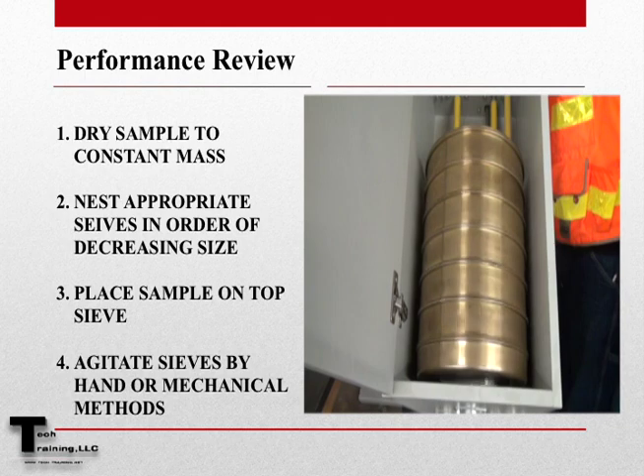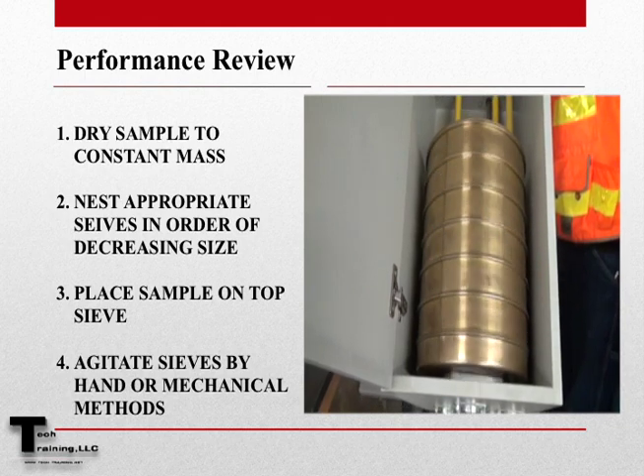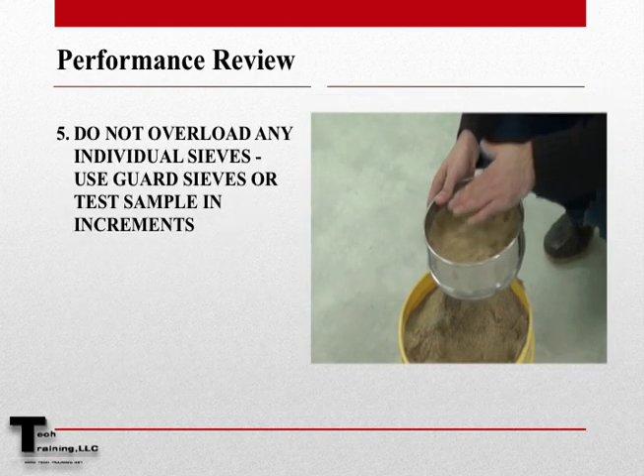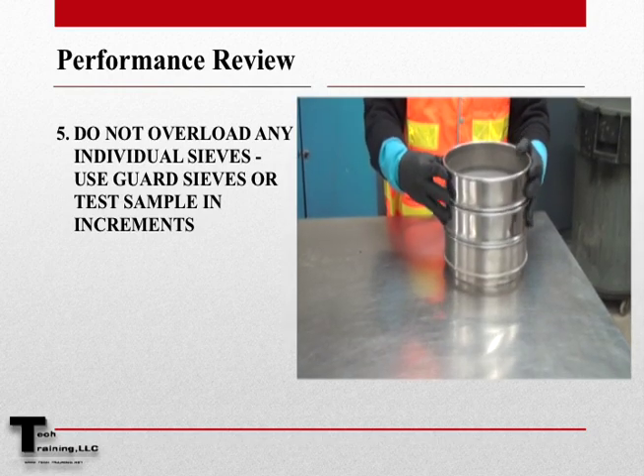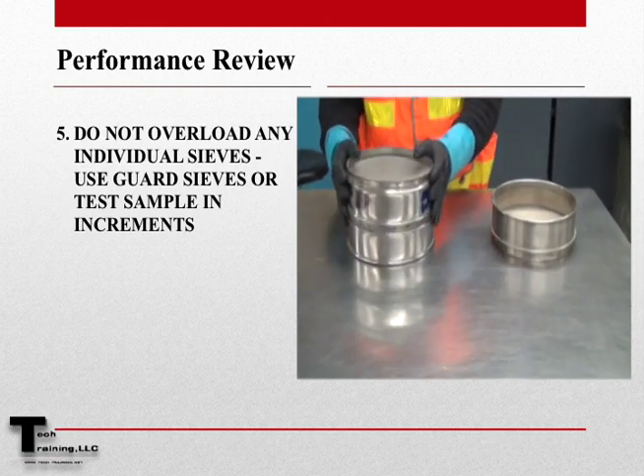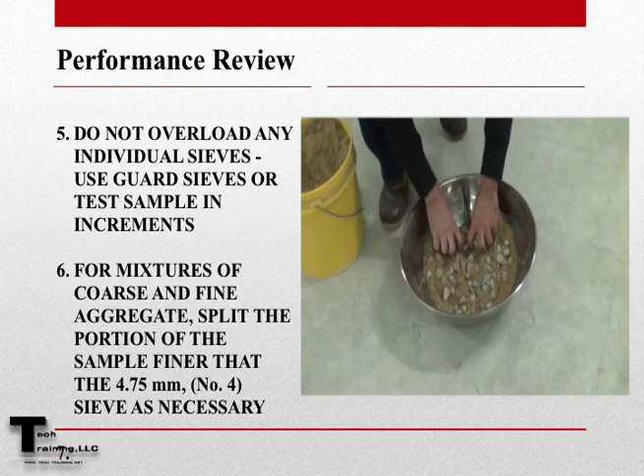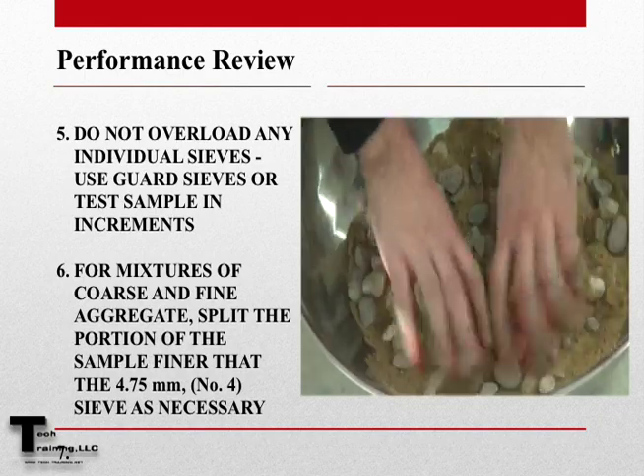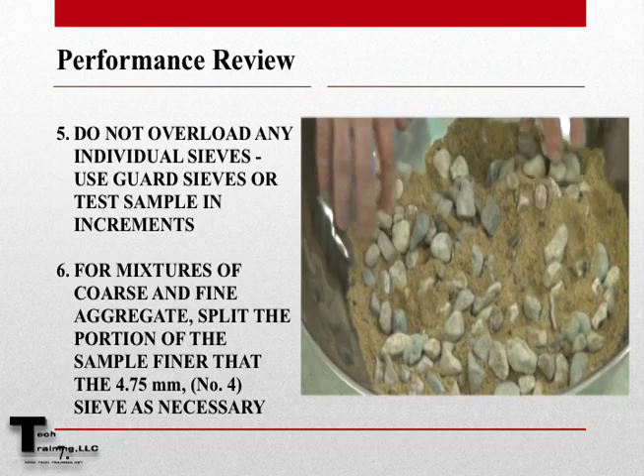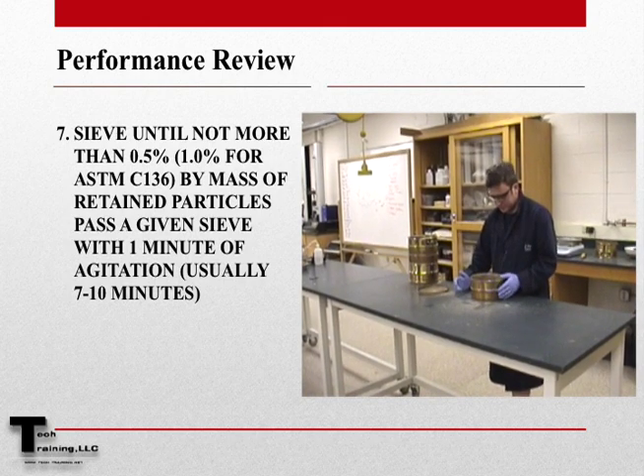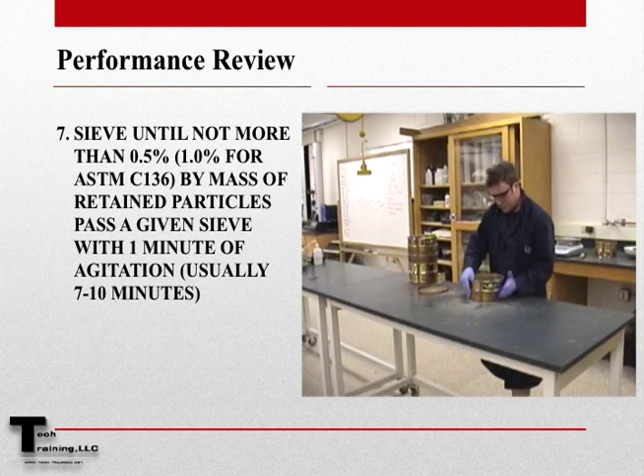We can now agitate the sample by hand or mechanical means. Be sure not to overload any individual sieve. Use guard sieves if necessary, or test the sample in separate size increments. For mixtures of coarse and fine aggregate, split the portion of the sample finer than the 4.75 millimeter, or number 4 sieve, as necessary.